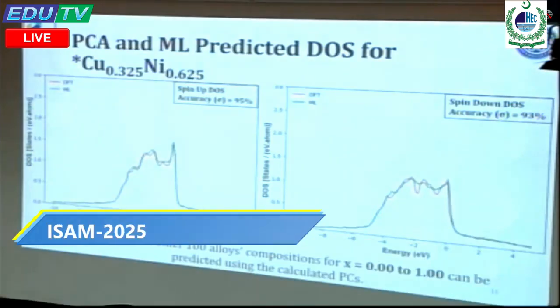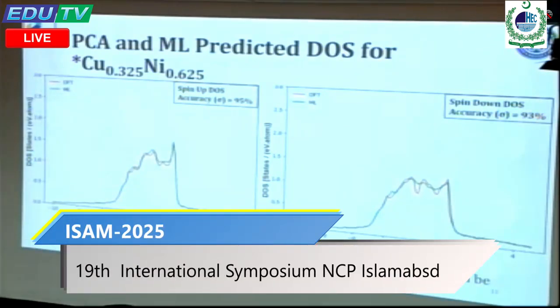And here are the predictive results from the machine learning model and PCA. This is the density of states for the spin up direction, where 95% accuracy was achieved, and this is the spin down density of states, where 93% accuracy was obtained. And you can see we can also calculate the density of states for 100 other alloy compositions from x = 0 to 1, that is from 0% copper to 100% copper and 0% nickel to 100% nickel, by using the calculated PCs we calculated earlier.